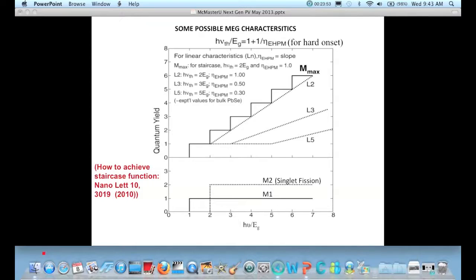Most of the data in the literature shows that you don't have a step-like function, you have a linear function. So there's a threshold for the multiplication, after which you get a linear increase in the quantum yield versus photon energy. And we showed in this paper that the threshold is related to the efficiency. The efficiency is the slope of the line. It tells you how many electron hole pairs you get per additional band gap of excitation beyond the threshold. The best you can do is a threshold of 2. If you have a threshold of 2, you'd have 2 electron hole pairs produced when you're at twice the gap. And then as you go to 3, you'd get 3 and so forth.